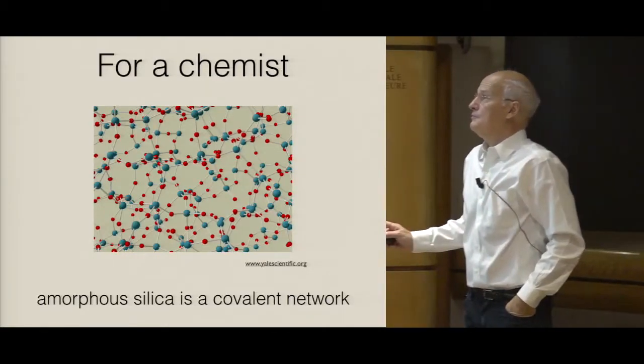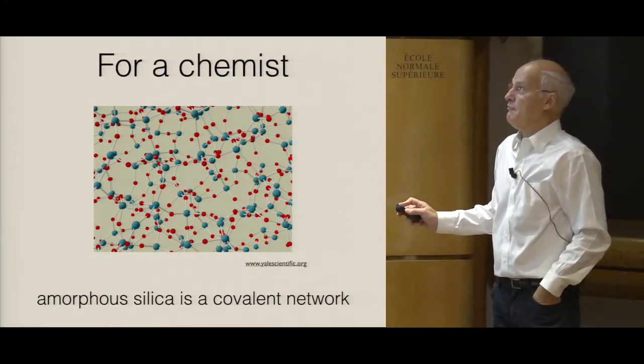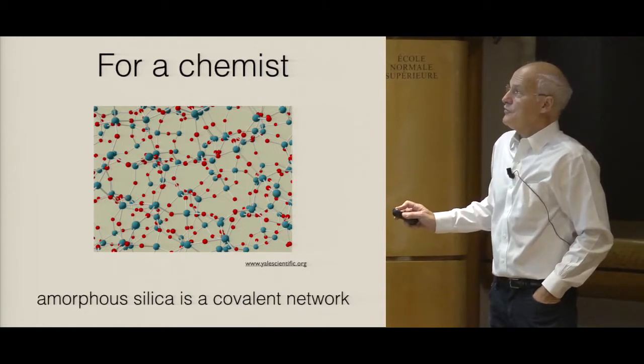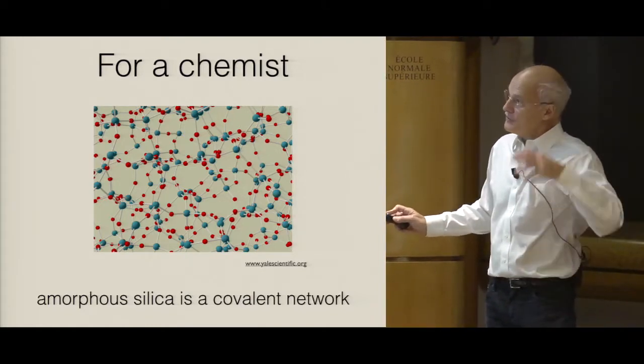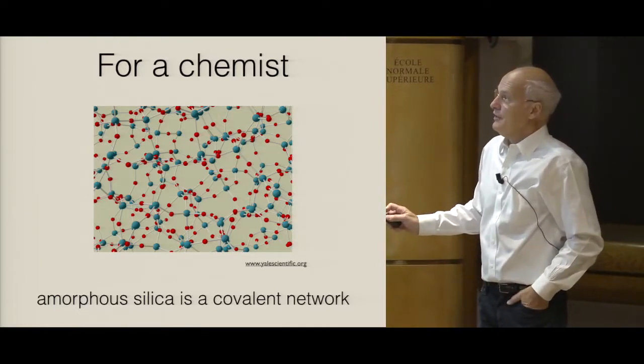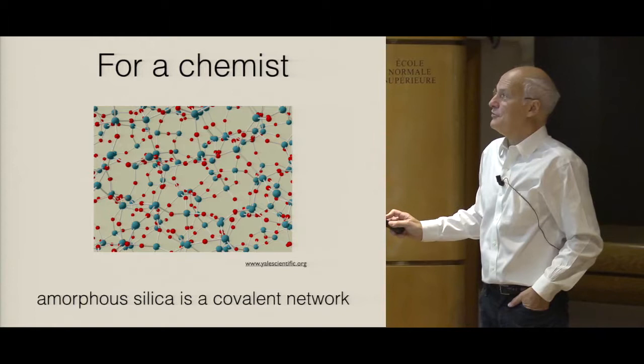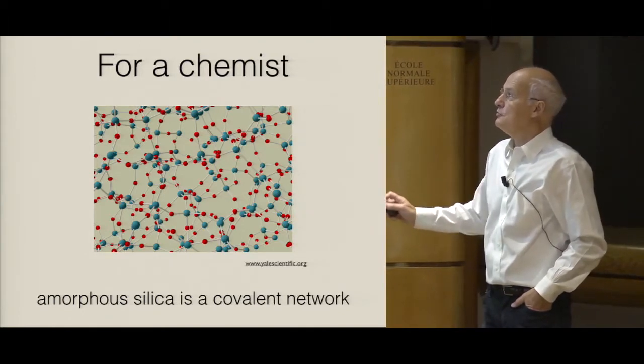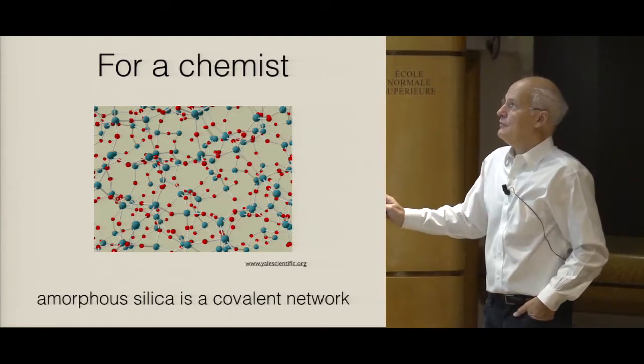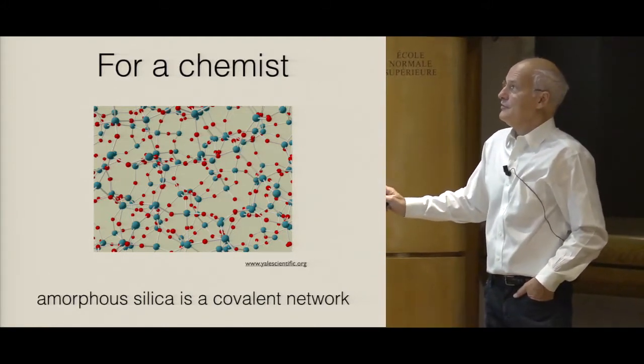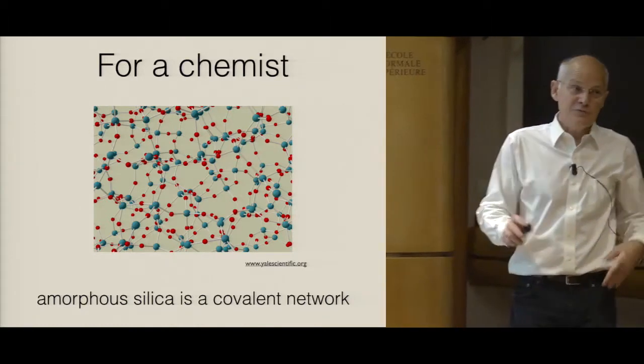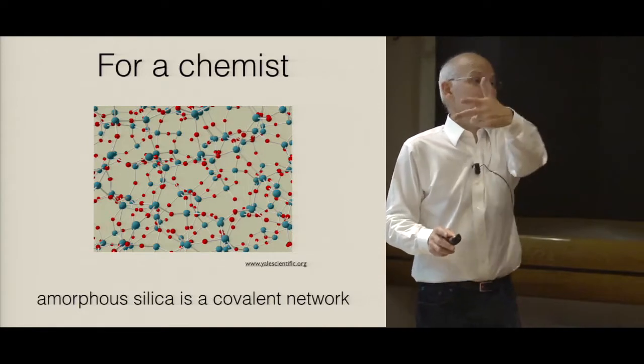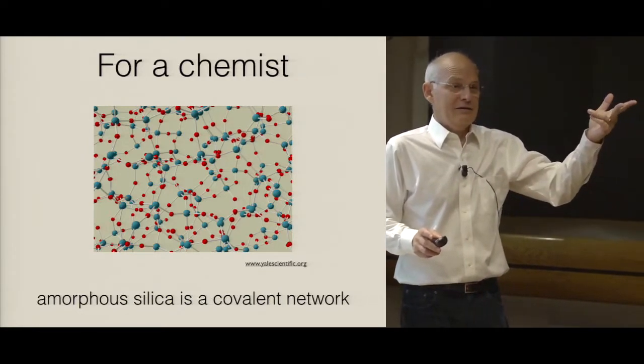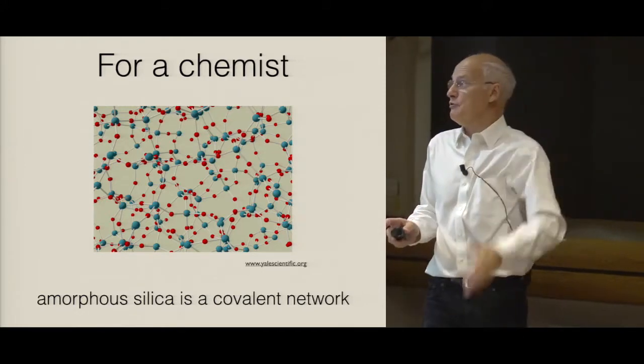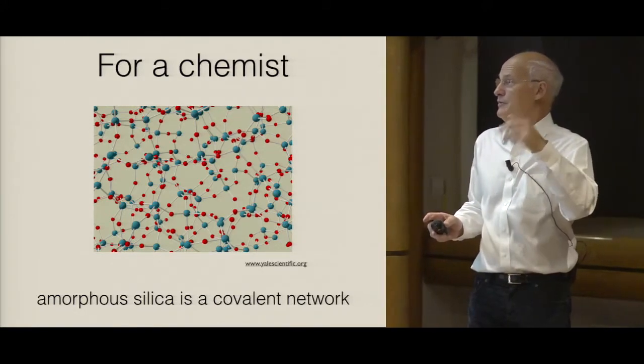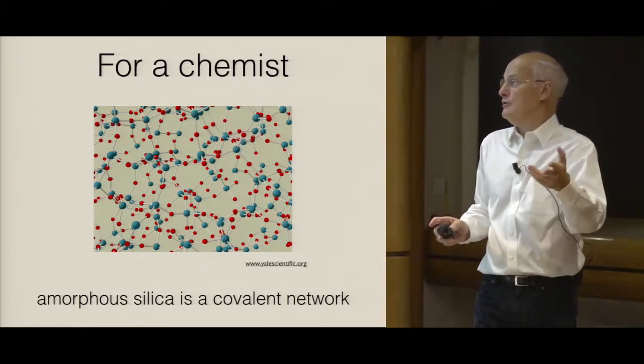And why I say it's a very intriguing behavior is because silica is a network. It's a covalent network, so it's like the polymer networks that we introduced at the beginning. There are silicon and oxygen atoms, and they are linked into a covalent disordered network. So this is the vision that the chemist will have. And of course, once you say it's a network, then it's obvious that it's not soluble, unless you break the bonds, which you can do chemically with a very strong acid. But then the question is why it flows.